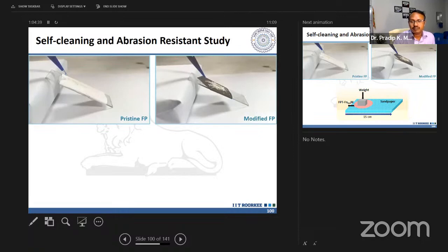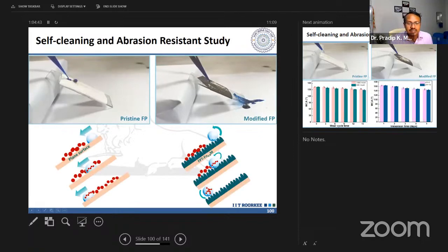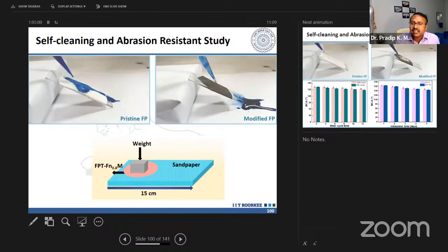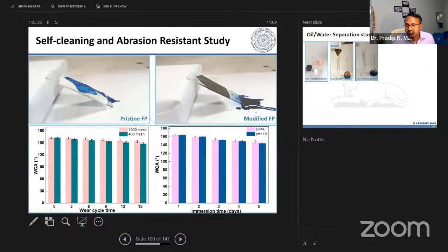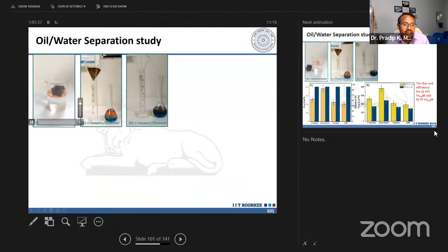Now this is basically the mechanism. If it is the unmodified sample, the contact angle is very, very low, so it will adhere with other material. But here, the water takes a ball shape, it will roll and take the dirt particles with it. And we have checked whether this material can be used many times. We used sandpaper to check abrasion. After the abrasion, the contact angle has not changed too much. We have also checked the contact angle after utilization at different pH and different mesh, and the contact angle is almost the same. Means after reuse and long duration of utilization, the material can be used many times.